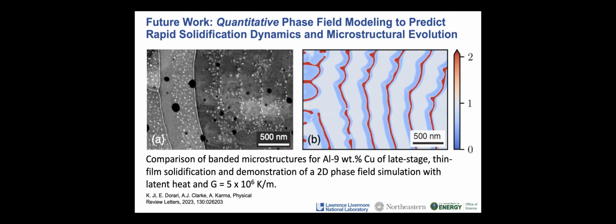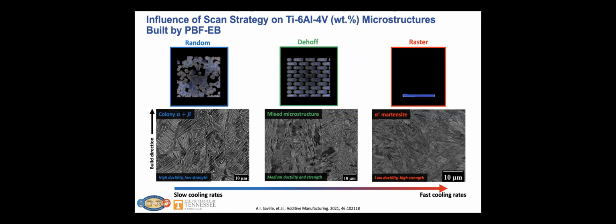So this is the first quantitative model that actually predicts microstructures that we see predicted from theory, even at very high solidification velocities. In this case, on the order of 1 to 2 meters per second in aluminum copper. We're comparing this to another experimental technique that we do with Lawrence Livermore National Laboratory called dynamic transmission electron microscopy, where we hit a sample with a laser and we're able to watch solidification at 1 to 2 meters per second. And in this case, we form some banded microstructures that we see that are predicted. And we're able to quantitatively predict that. So now, armed with this new model applicable to rapid solidification, these GV conditions that we can get from our process simulations, we're now in a position where we can start doing predictive microstructure modeling.